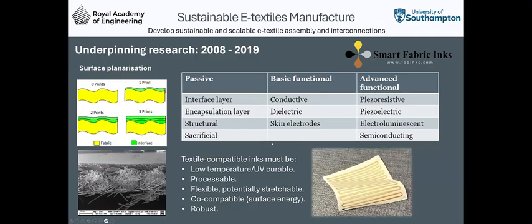Just to give you an idea of some of the inks we've developed. We have developed an interface ink that you coat the surface of the textile with. You have to do this to make a nice smooth textile surface. Otherwise, you've got a very fluffy, rough surface to print on, and that's very, very challenging. Other layers include encapsulating layers, basic functional layers, conductive inks, dielectric inks, electrode inks that are designed to interface with the skin for ECG monitoring, for example, and then more advanced functional inks, so piezoresistive strain sensing inks, piezoelectric, as we saw, electroluminescent, and even semiconducting inks. So we can print transistors now onto textiles.